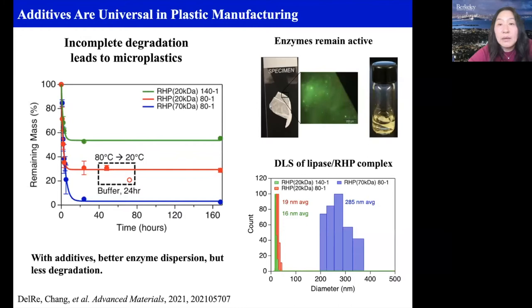a small amount of additive in the system, only 1 or 2%, can lead to a significant change in the level of degradation. So we have a system where we can get nearly over 95% degradation, polymer to small molecule conversion. But as we're adding the additive, in exactly the same system, just a little bit of additive in there, you can see they stop at 50% and do not degrade further. So we only leave this microplastic behind. We tried to reset the thermal history to see if we could get the system to degrade a little more. The system can be reset. We can gain another 10% of degradation, but we can never achieve near complete degradation.